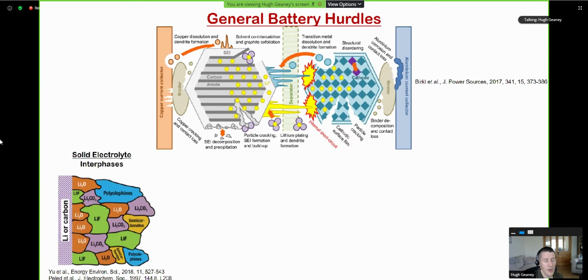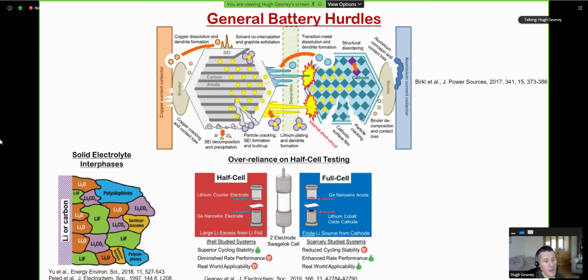In terms of general battery hurdles, as a general comment, there's definitely an over-reliance on what's called half-cell testing. On the left-hand side, we have a half cell, which is our active material. In this case, it was germanium nanowires that we used, tested versus a lithium counter electrode. What people will tend to do if they make a new material for a battery system is just test it in a half cell versus lithium or sodium or potassium.